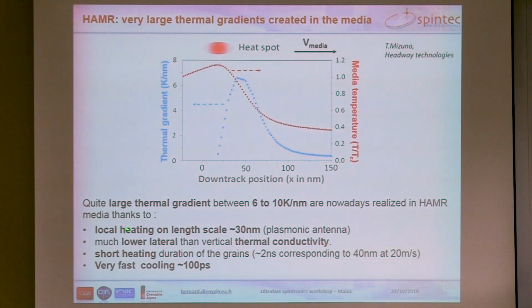And this is due to this combination of heating on a narrow length scale, together with also, in terms of conductivity, the vertical conductivity in the media being much higher than the lateral conductivity. And the heating is very short, 2 nanoseconds, typically, which corresponds actually to the motion underneath the plasmonic antenna, of the order of 40 nanometer wide at a velocity of 20 meters per second.